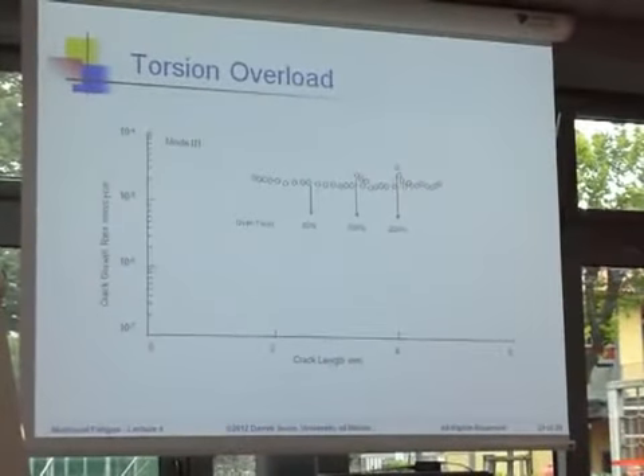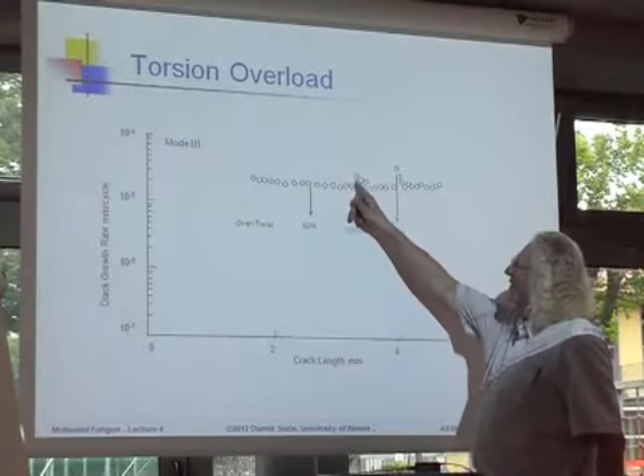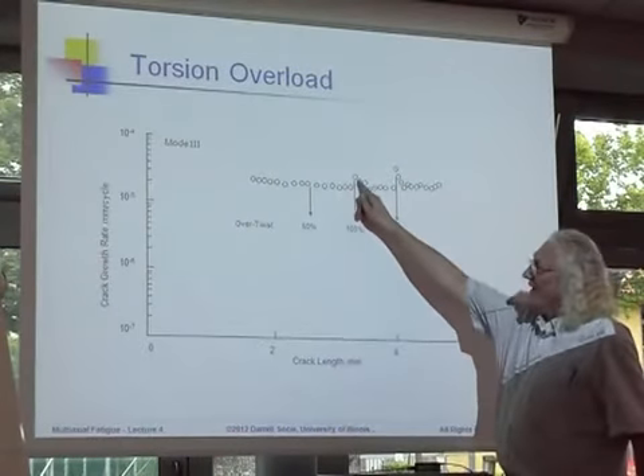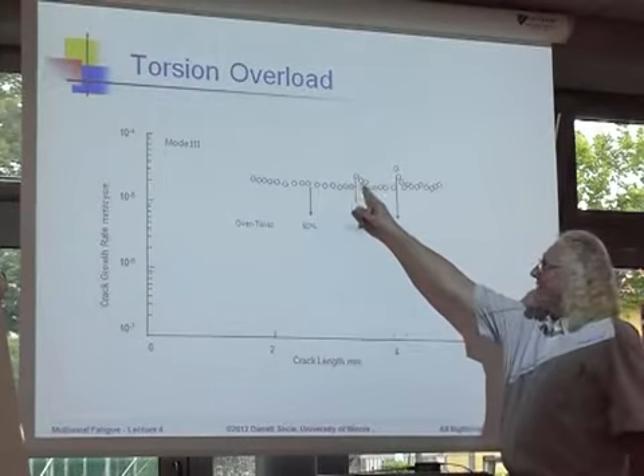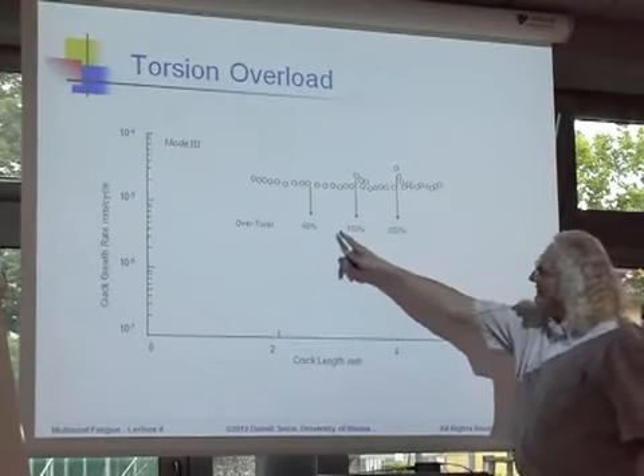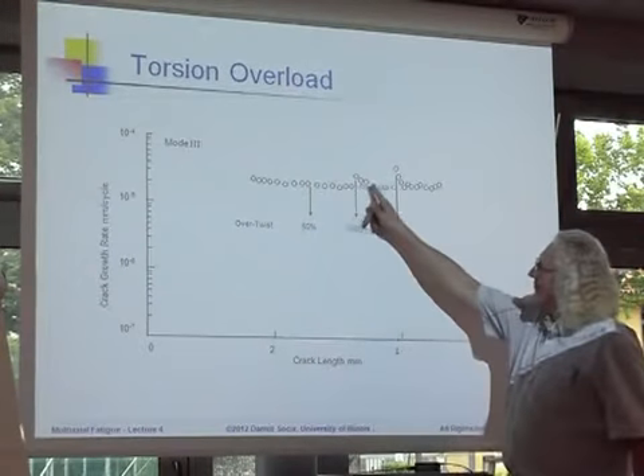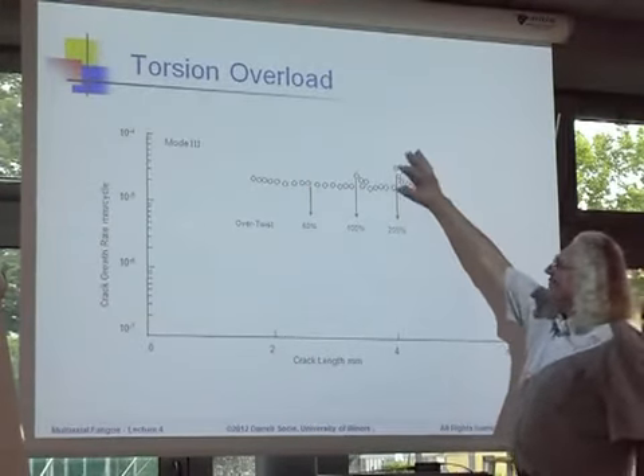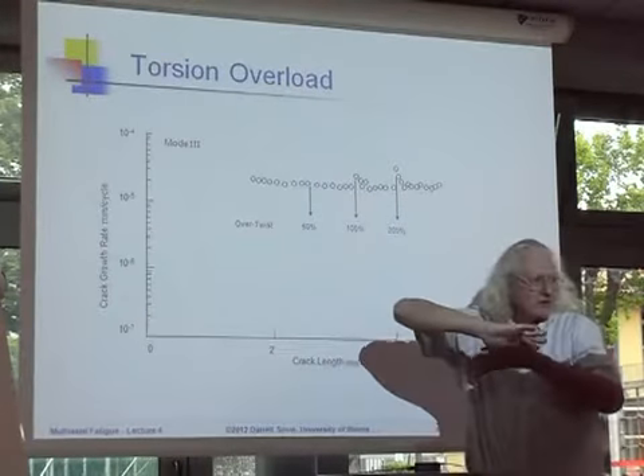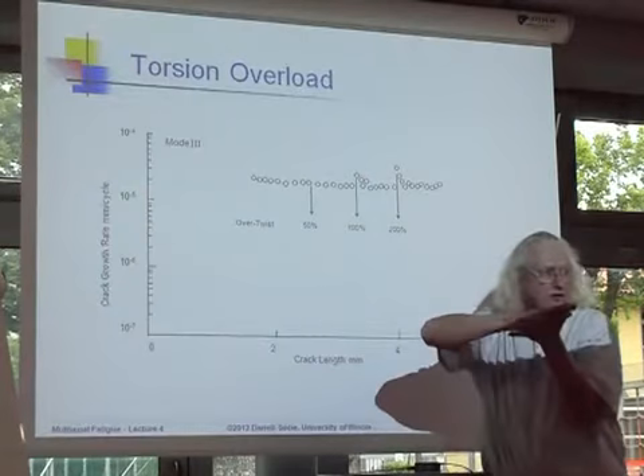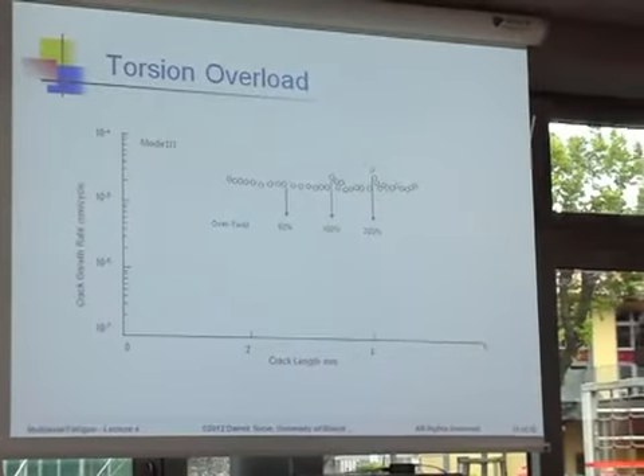How about the experiments? What did the experiments show? No, we have to look. Worse, right? Because after you apply an overload in torsion, you can see that the growth rate actually increases. And then it goes back to the growth rate. And what's different about these is this is overloading 50%, 100%, and 200%. You can see the amount of acceleration in crack growth depends on how much twisting I have, because I'm changing the crack face friction. And that has more to do with the growth rate than anything else.